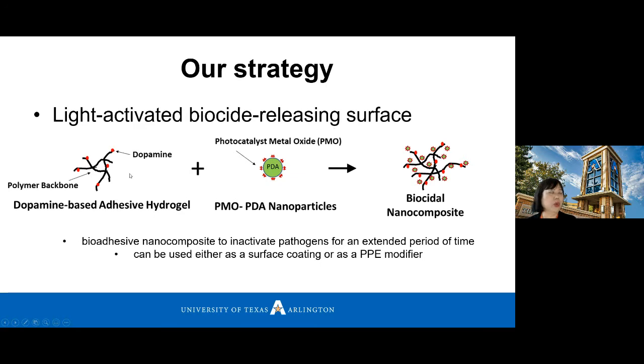How do we do that? We develop a dopamine-based adhesive hydrogel. Dopamine mimics mussel adhesive property. So this hydrogel will adhere to the surface very tightly because it mimics the mussel adhesive property. You know, the mussel adheres on wet surfaces very strongly. So this dopamine-based adhesive hydrogel will stick on the surface very strongly.